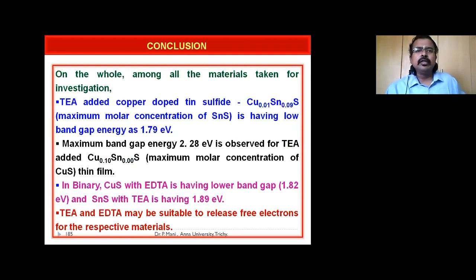Conclusion for the experiment: on the whole, among all the materials taken for investigation, TEA added copper doped tin sulfide, that is CTS, has the lowest band gap energy, 1.79 electron volt. The maximum band gap energy, 2.28 electron volt, is observed for TEA added CTS.